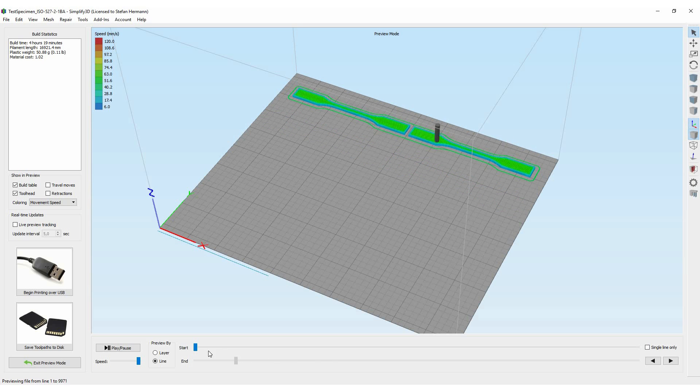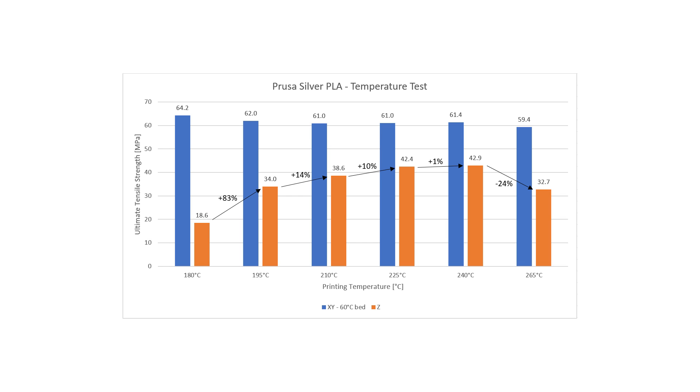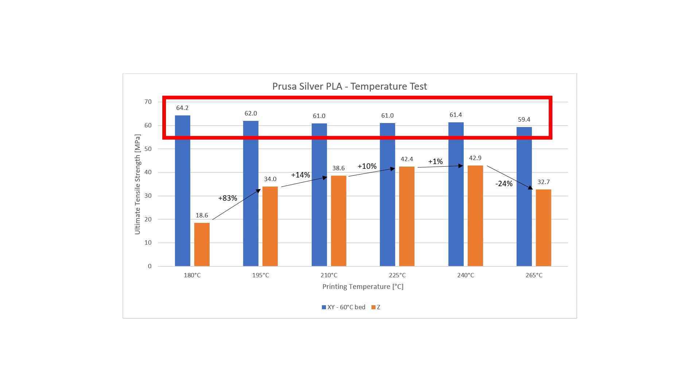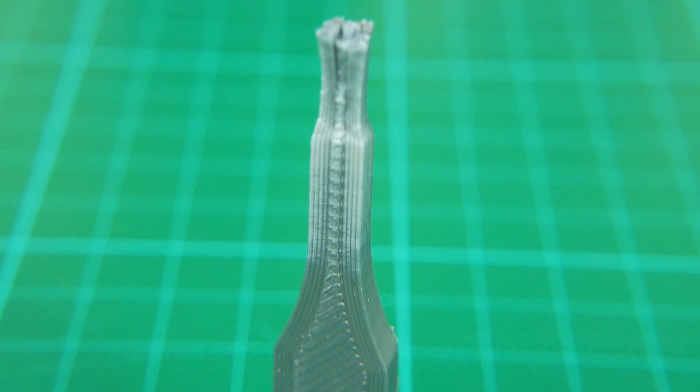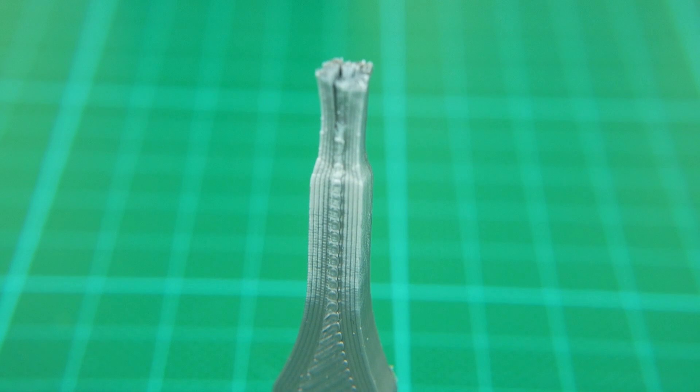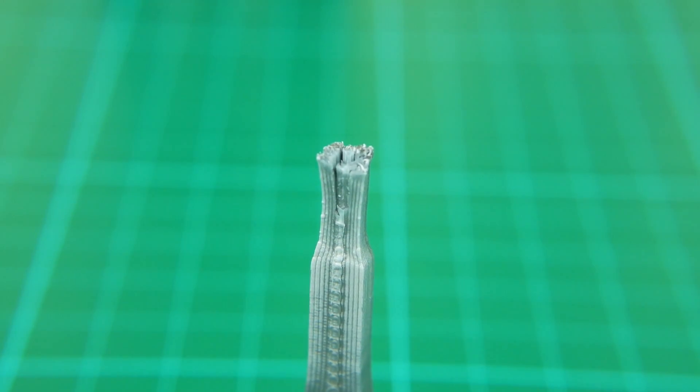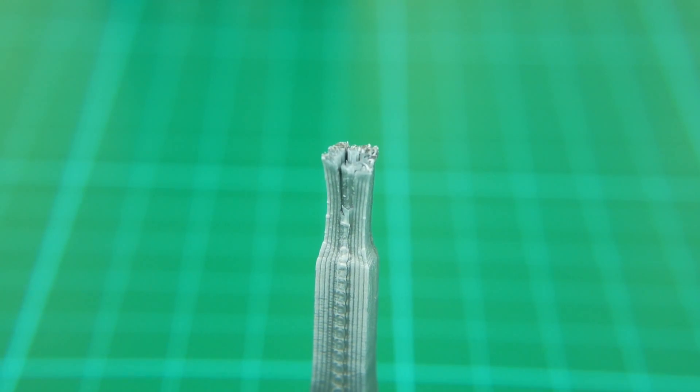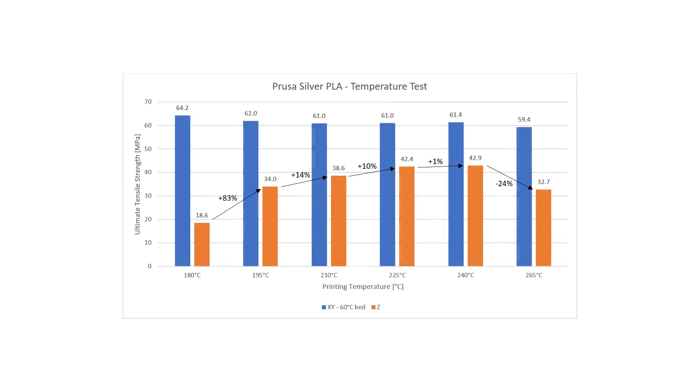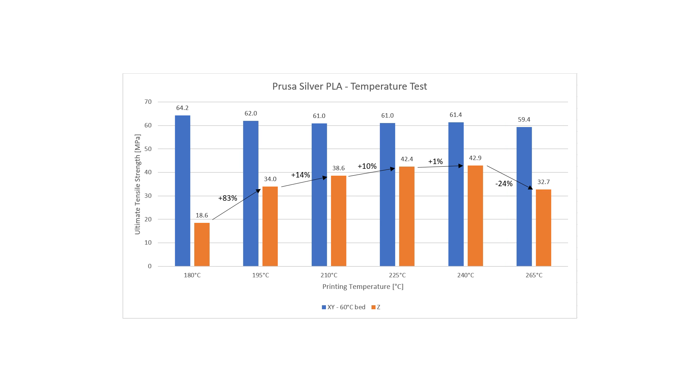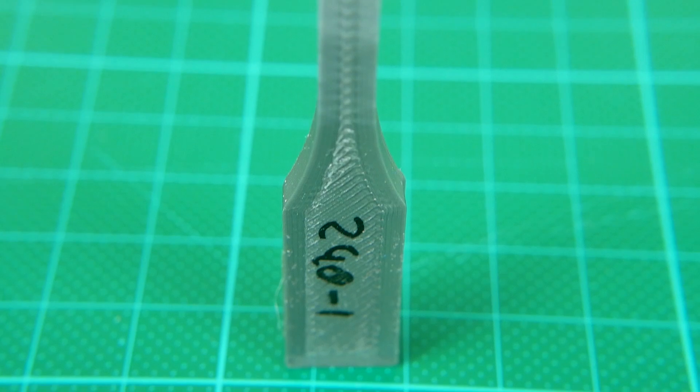Let's take a look at the results. The strength of the lying specimens was quite constant and wasn't influenced too much by the print temperature. The specimens printed at 180 degrees were a little bit stronger and they did not show a brittle failure like the others. But if you take a look at the fracture surface, you can see that the material did not perfectly fuse together, so some filament strands are still visible. The specimens which were printed at 265 degrees Celsius had a slightly smaller strength, probably because the material already degenerates at these temperatures and the forming of bubbles creates weak points. All of the other ones were pretty much the same, with fracture surfaces becoming more and more homogeneous with higher temperatures, which shows that everything is fusing together with more heat.